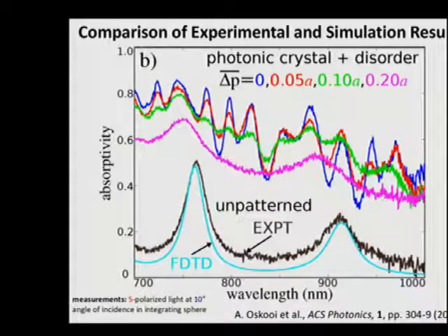I also demonstrated experimentally the peak broadening effect that I had predicted using the simulations. As you can see here, again, an increasing amount of disorder applied to the photonic crystal lattice tends to broaden the peaks. I also found good agreement between the experimental and the simulated absorptivity spectra for an unpatterned film, which suggests that my modeling was indeed accurate.